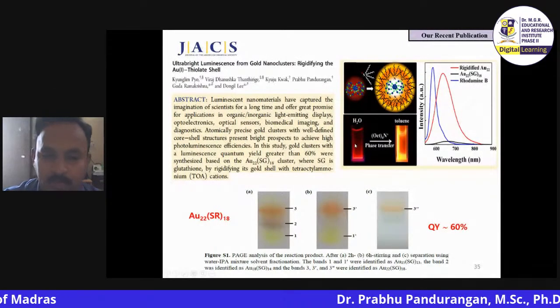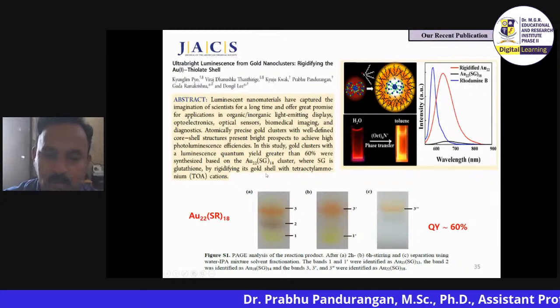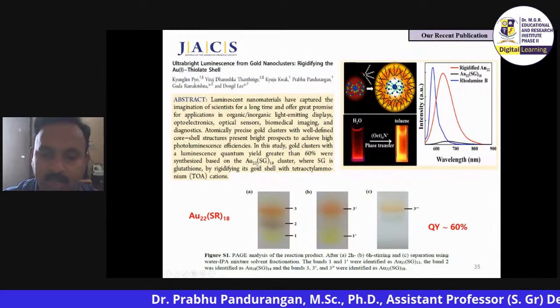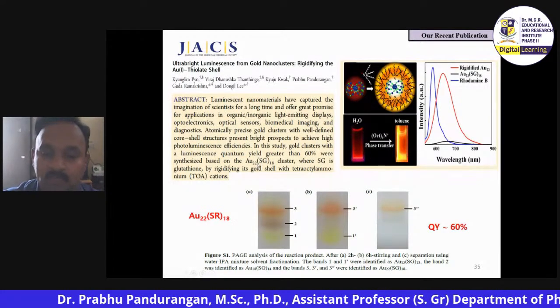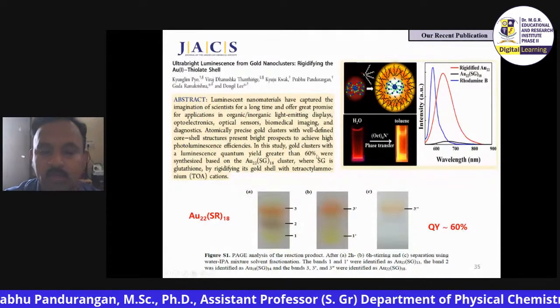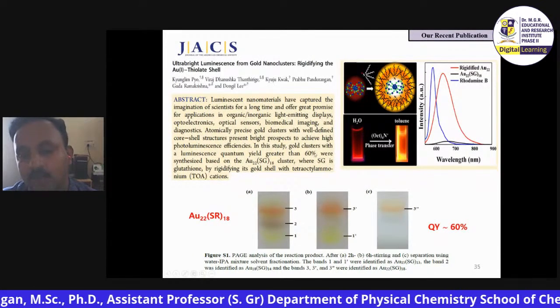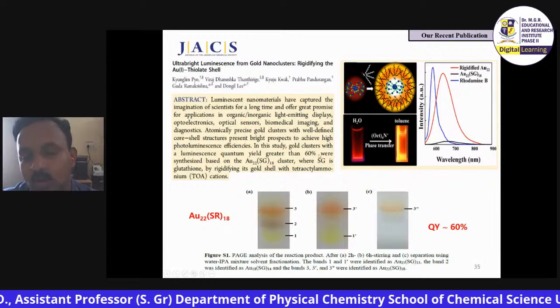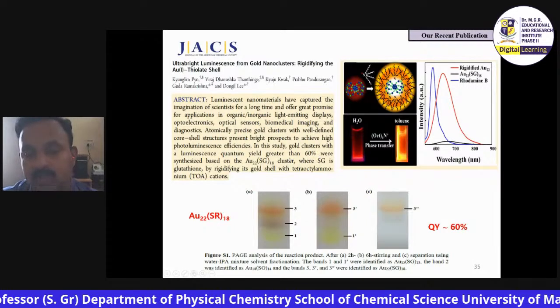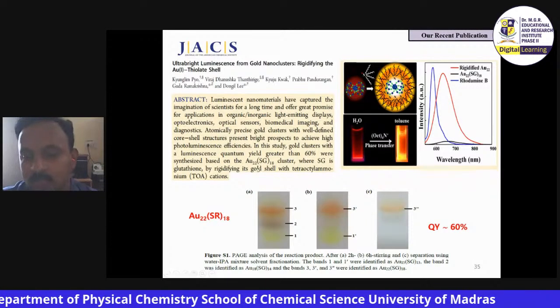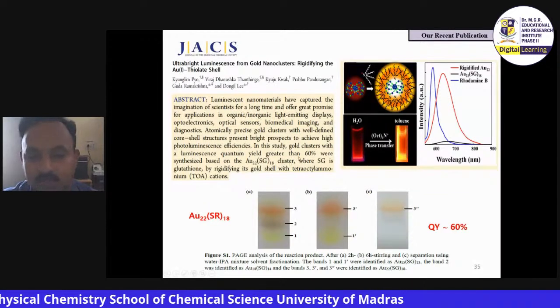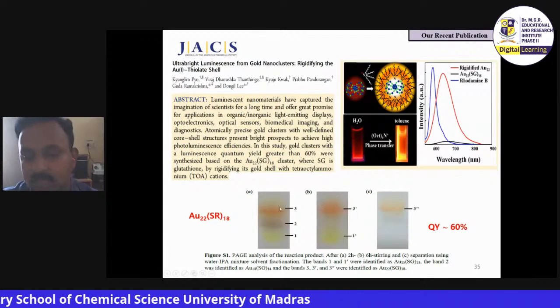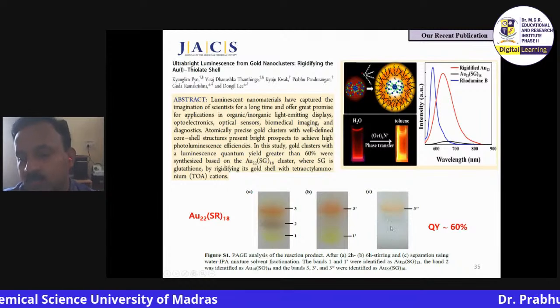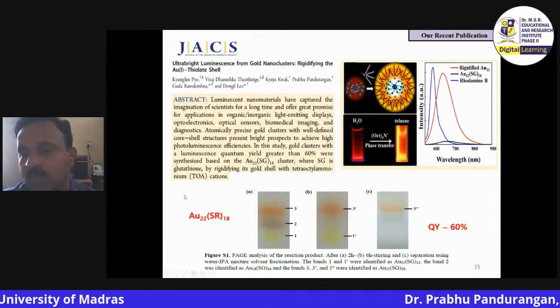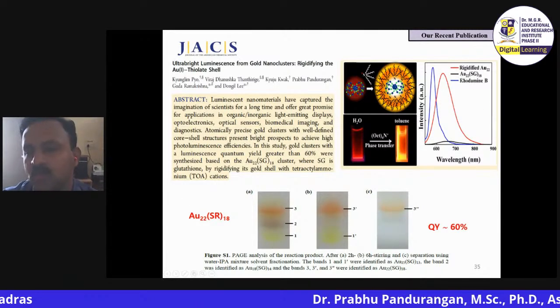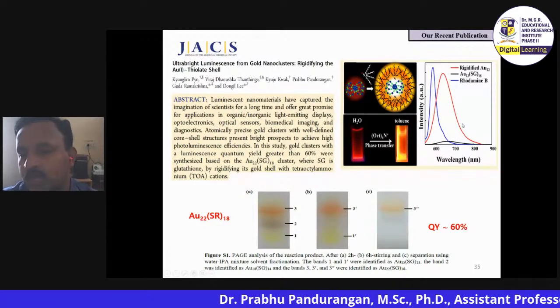The beauty of this paper is that before this paper, gold 25 and gold 22 had 8% quantum yield. But this paper reported the highest quantum yield of 60%. Even a 0.5% increase in quantum yield in photochemistry papers is extraordinary, but here you can see from 8 to 60%. These are the gel separations done by the postgraduate student based on my experience. And you can see the response of this gold 22 is like this.